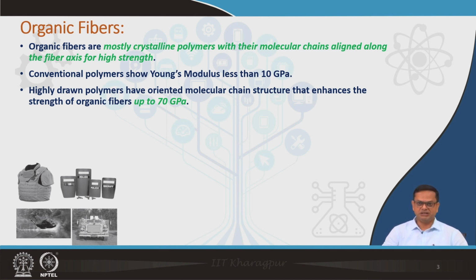Obviously, I mentioned boron fiber in the last class, and I have talked about glass fiber and carbon fibers also. Those fibers show very high strength and modulus, but organic fibers definitely do not show that high strength and modulus. But there are a lot of commercial applications where you do not really need that high strength and modulus, but you need fibers which show fairly high strength and modulus, and which you can produce easily without much expenditure and many problems. Organic fibers come into that regime where fairly good strength and modulus can be achieved without much sweating, or without much expenditure.